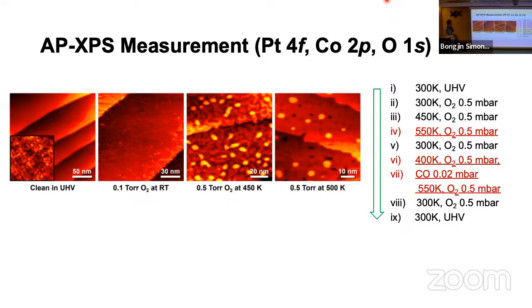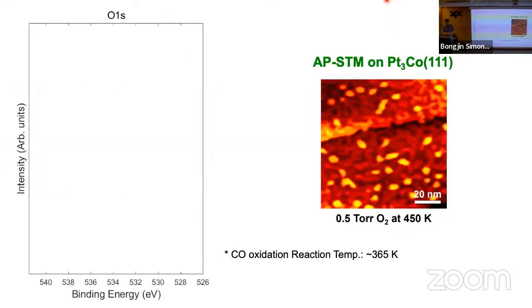And furthermore, we ran the CO oxidation experiment. But just looking at this, the size of the oxide is completely different from the platinum-3 nickel that we just saw. So obviously, platinum-3 cobalt behaves differently. So this was the STM image, and then we were following all this step together with the